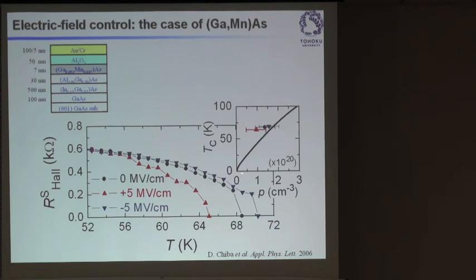And this is a comparison with hole concentration. We know the capacitance, and we know the change in the conductivity. So we can separate the carrier concentration and mobility, from which we can determine the total carrier concentration in the film. Divided by the film thickness, we can get this number, a hole concentration in cubic centimeters. And this is the model calculation, the p-d Zener model. And as you can see, it also accounts for the magnitude of the transition temperature.